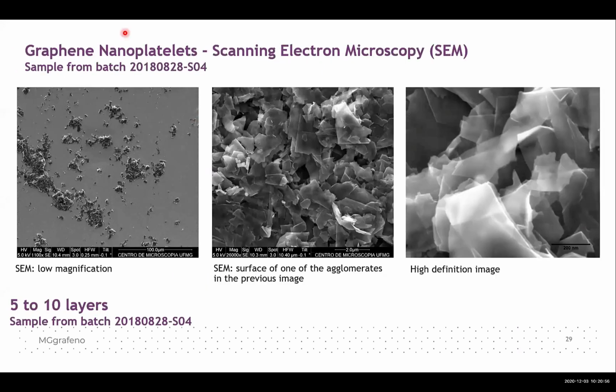So this is the graphene nanoplatelets. So this is the material that we call from 5 to 10 layers, how the material looks in powder. So this is deposited, of course, over substrate. So these are the SEM images of the material as it is. So you can see that it's really very finely exfoliated material.